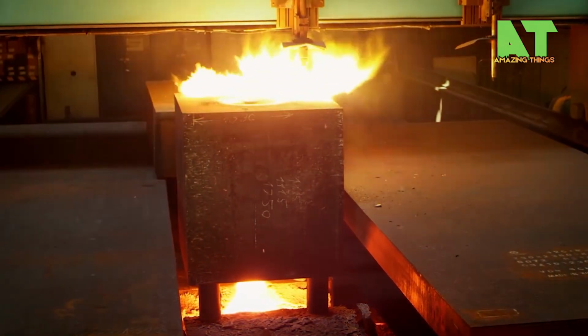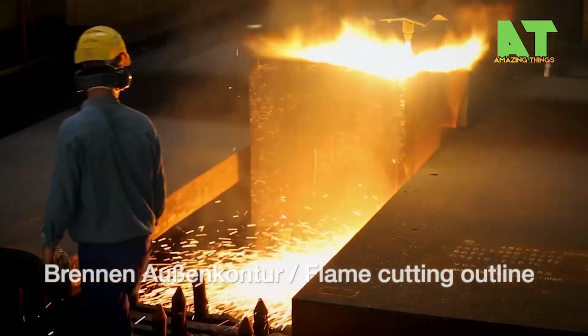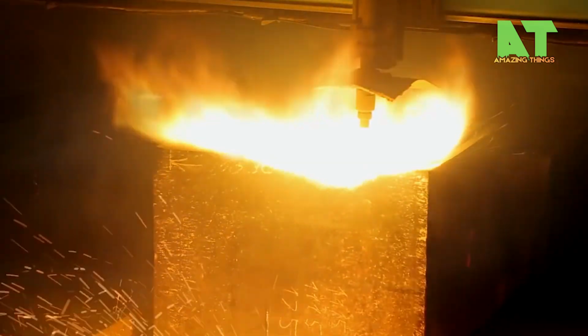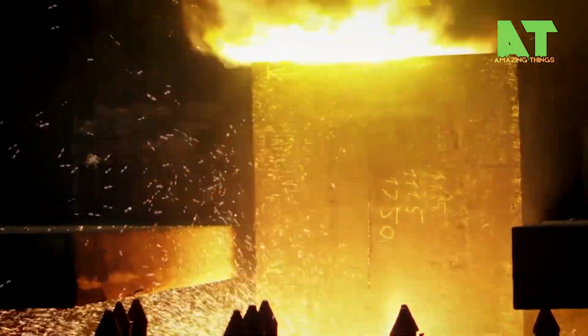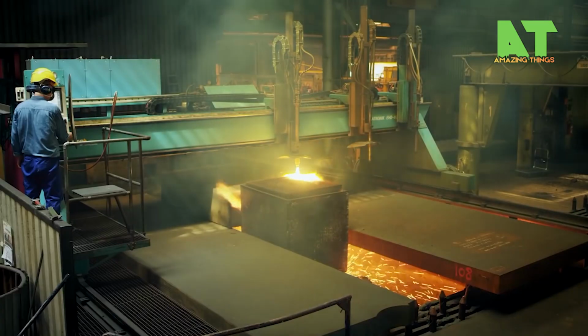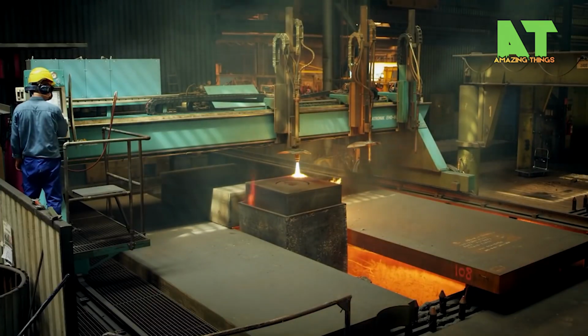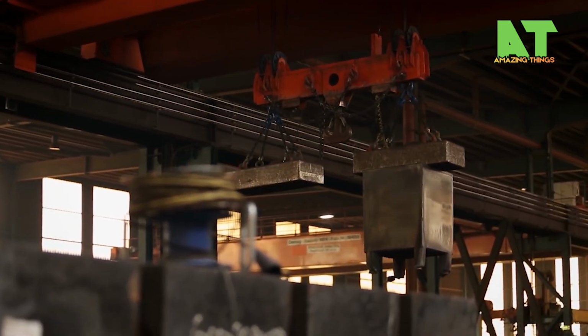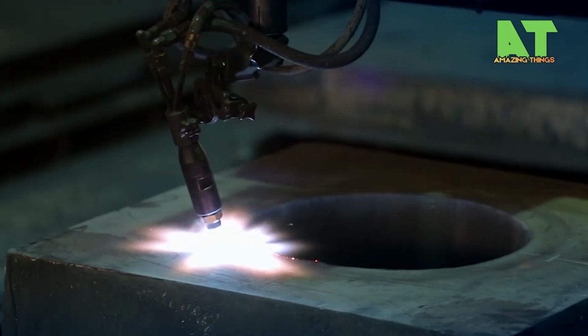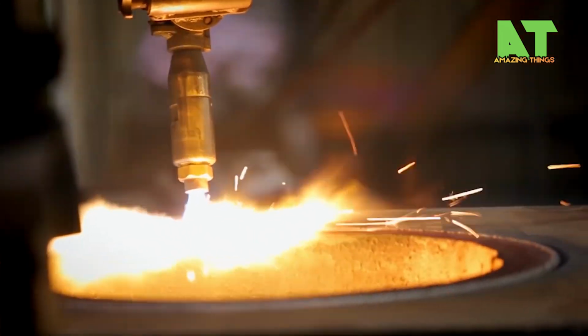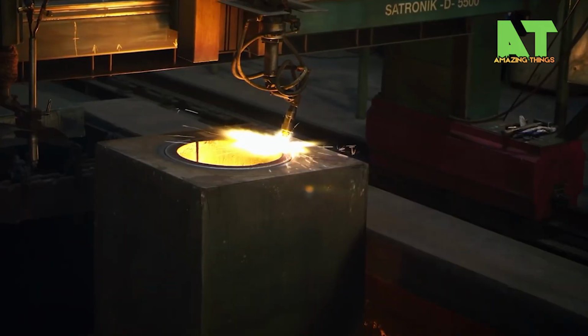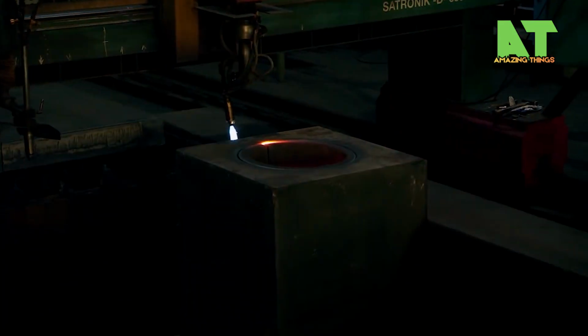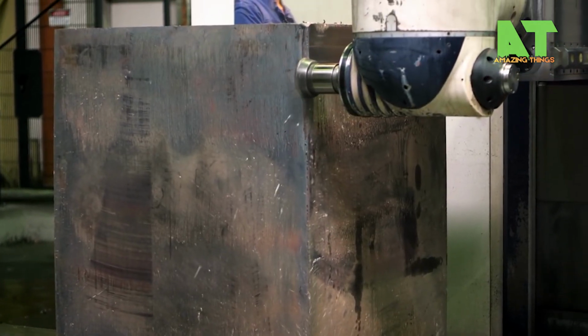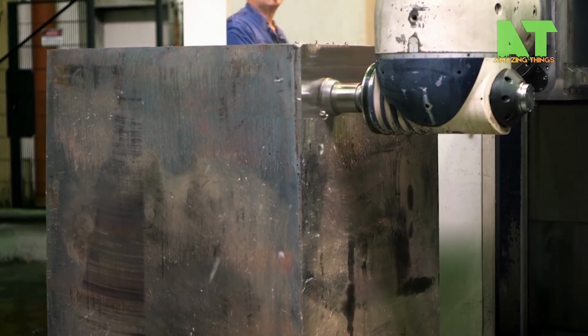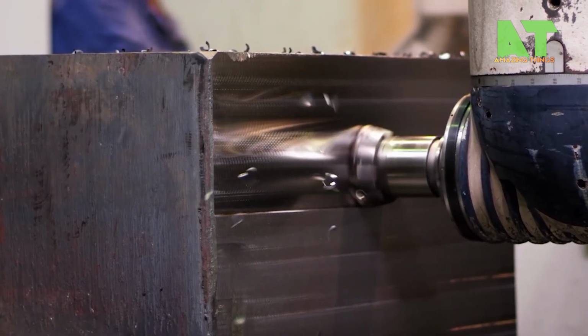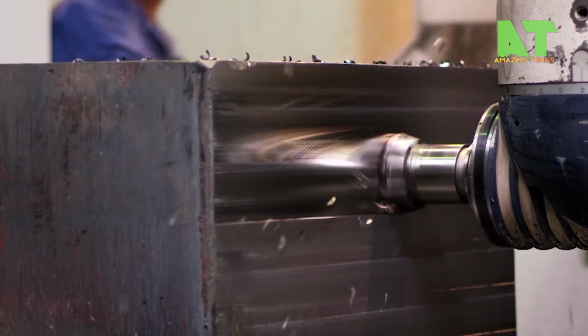What you're witnessing is the cutting oxygen stream traveling at supersonic speed, literally blowing molten steel and iron oxide out of the cut zone. That spectacular shower of sparks? That's the oxidized metal being expelled from the kerf, the gap created by the cut. For steel this thick, the torch moves deliberately slow, perhaps just a few inches per minute, ensuring complete penetration. The operator must maintain precise torch angle and distance from the work surface, skills that take years to master. Despite all our modern laser and plasma technologies, oxy-fuel cutting remains unbeatable for steel over 6 inches thick. Sometimes, the old ways really are the best ways.